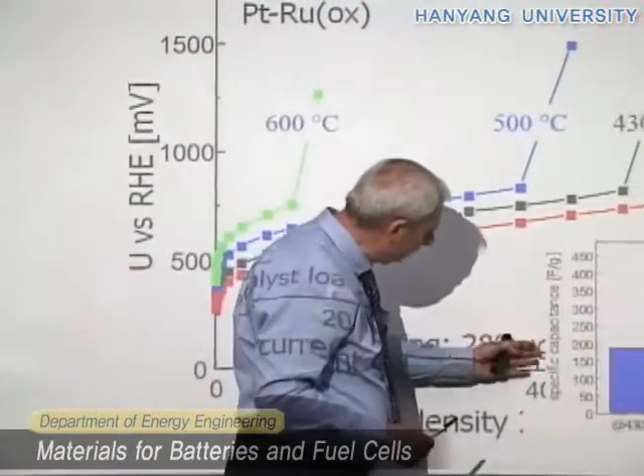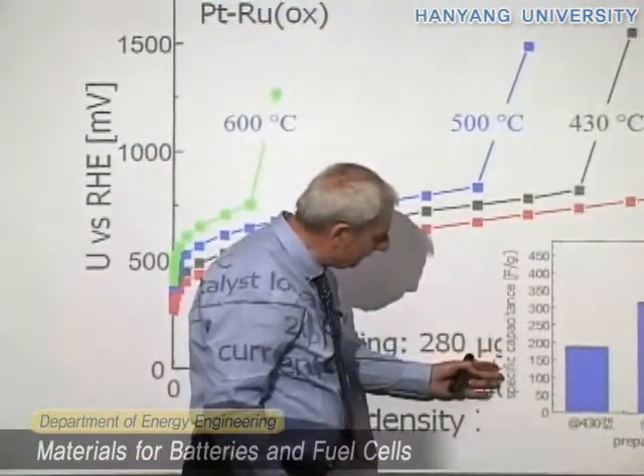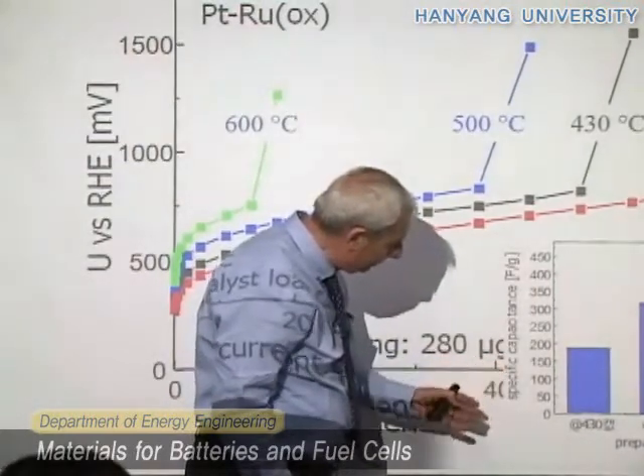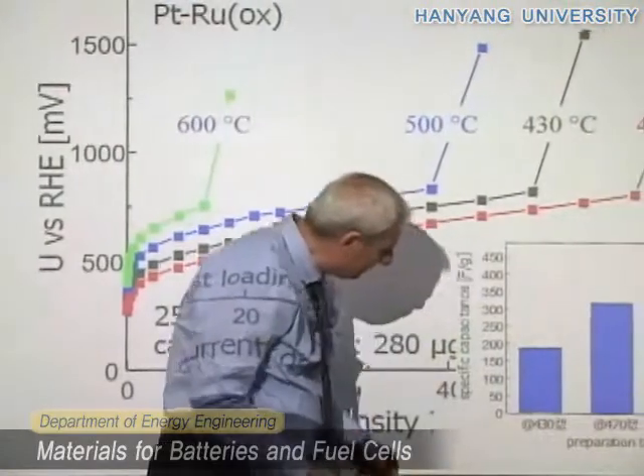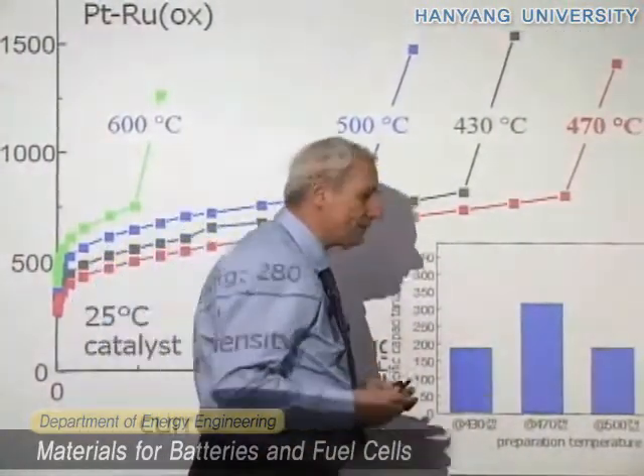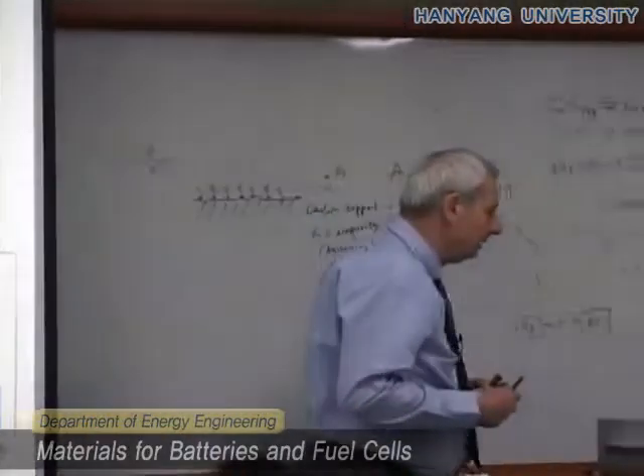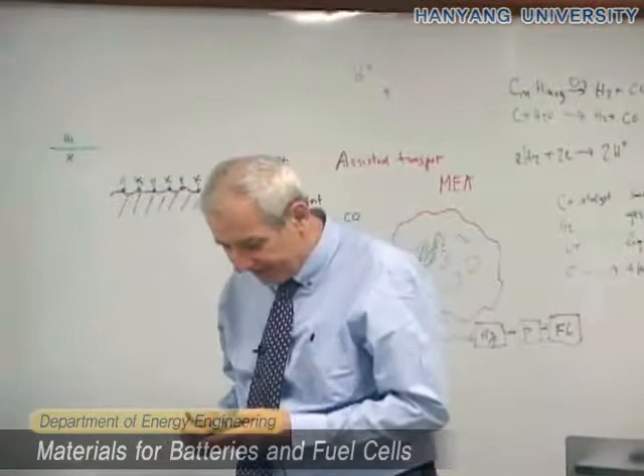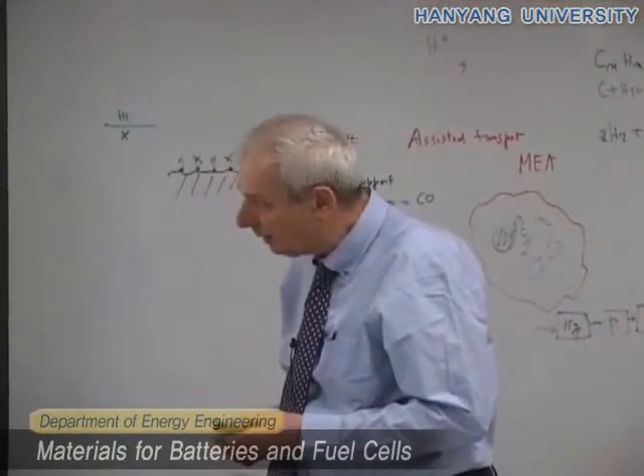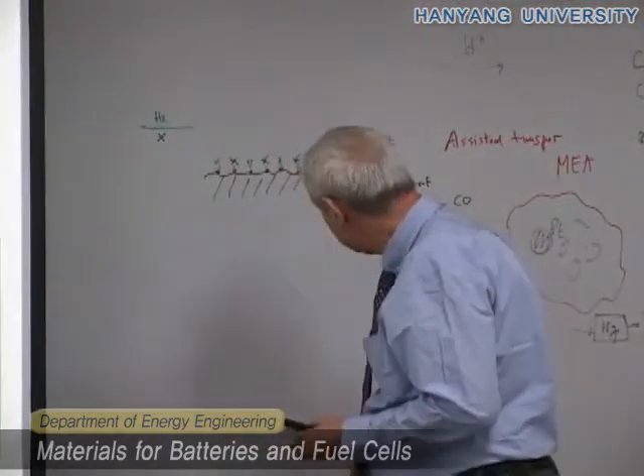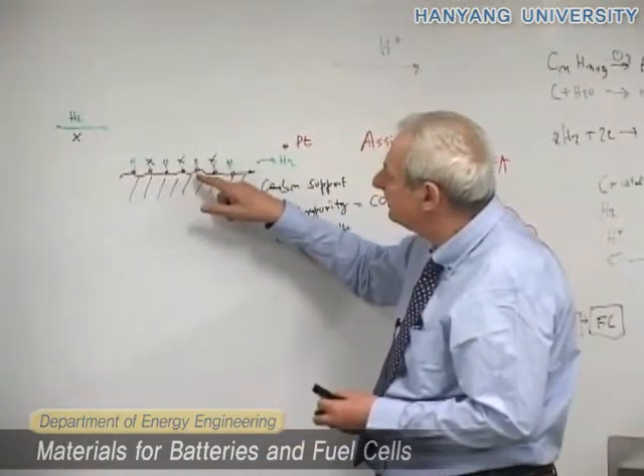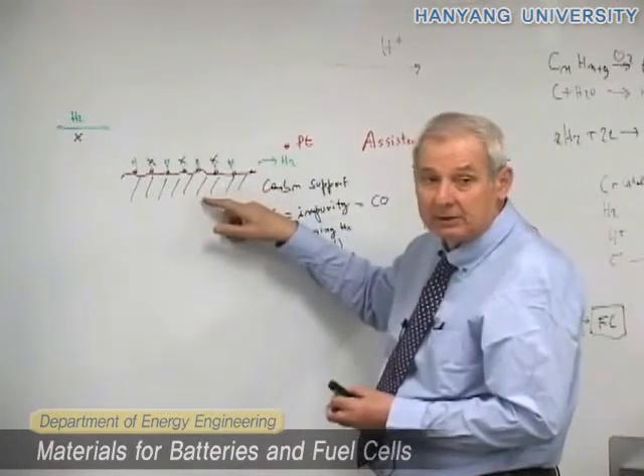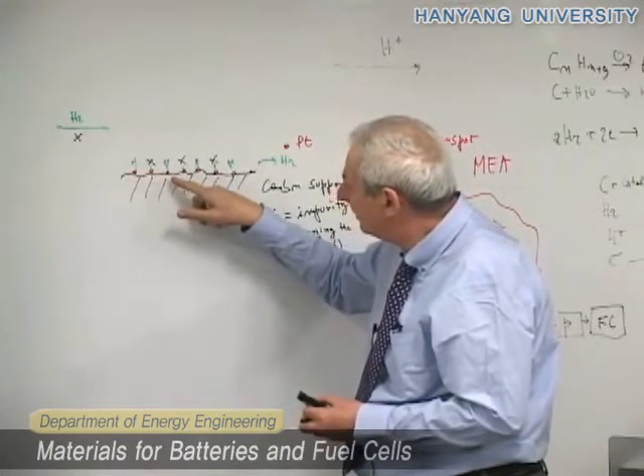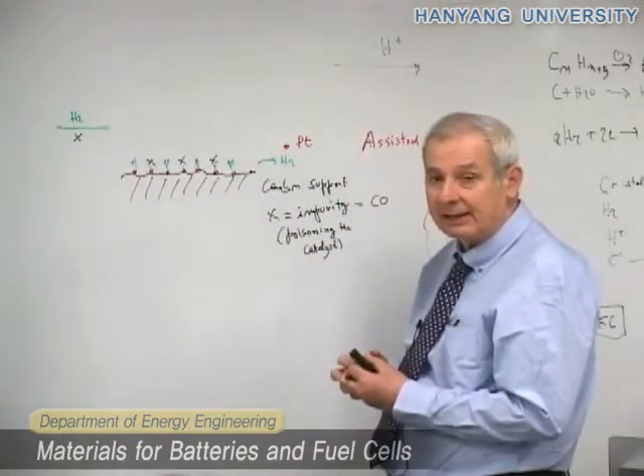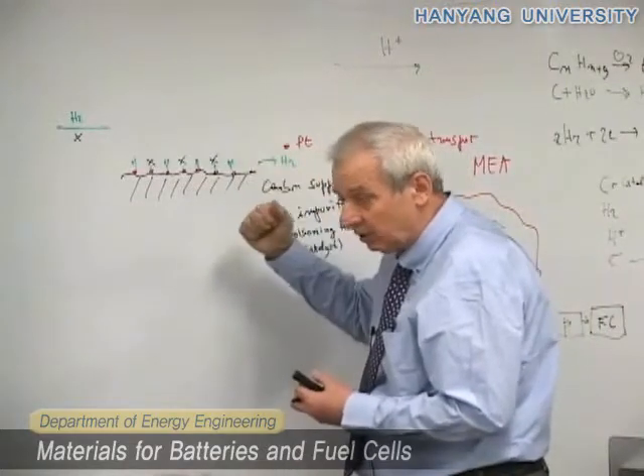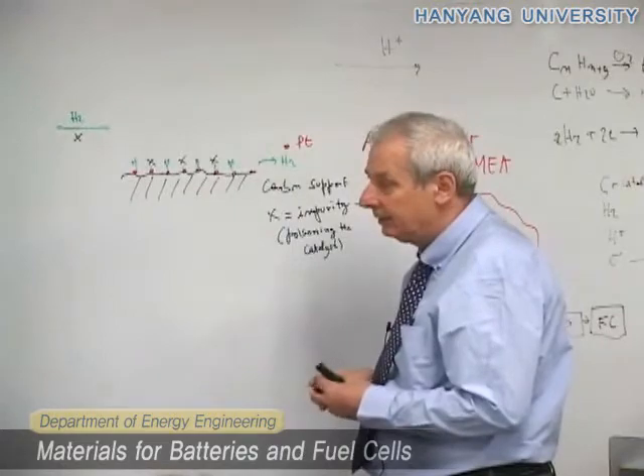And here, in fact, is reported the activity of the various catalysts. And you see that the best condition is given by the catalyst prepared at 470. And why does this happen? This was one of the main problems to understand. And this is related to the crystallinity of the sample. And this is quite understandable because you have the same operation here. So the red dots are the catalyst particles, and this particle has to absorb the species to make the reaction go.